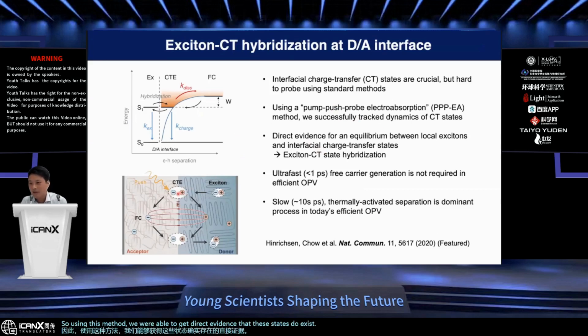And in fact, these states live for a long time. We first managed to see that these states have a lifetime way longer than 100 picoseconds. Essentially, the separation rate takes 100 picoseconds, but the fact that we are seeing a lot of them even beyond 100 picoseconds also tells us that once they thermally separate, upon recapture of the electrons and holes, they can actually repopulate this state. So essentially, what we have is an equilibrium being established between the CT state at the interface and the thermally separated free charges. We have this first direct evidence that the excitons, the CT states, and the free charges reach an equilibrium.